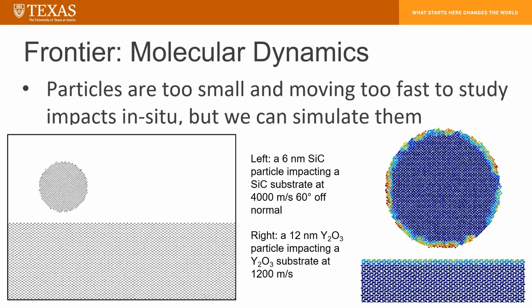And we have found that generally velocity is one of the most important impact characteristics to predicting what actually happens in our process. When it comes to actually figuring out what happens in impact, the particle impacts happen on such small length scales, nanometers or micrometers, at kilometers per second perhaps. And so these strain rates are too high to actually capture on a camera. There's no high speed that can really allow you to get that resolution in both space and time.